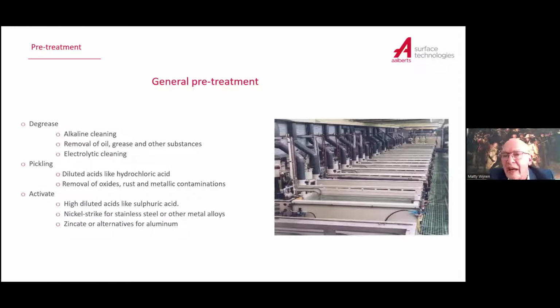To do this, you have to pre-treat your part. That's what I meant with the pre-treatment itself. It's not only one step in which you plate your part. No, you need a sequence of steps to make your part plated. If you look at the right picture, you see an immense amount of baths. I think I'm talking about 20 or 24 of these baths. Only two or three baths are really made just for plating. The rest of the baths are pre-treatment sections and rinsing sections.